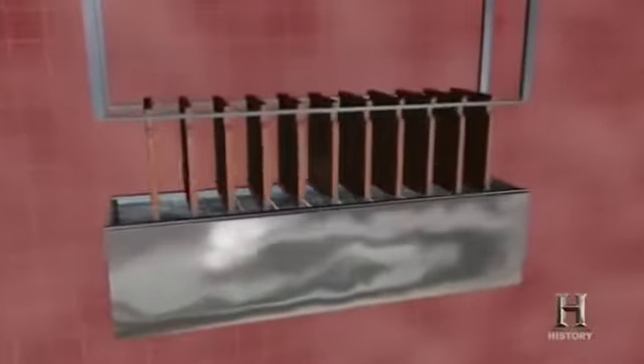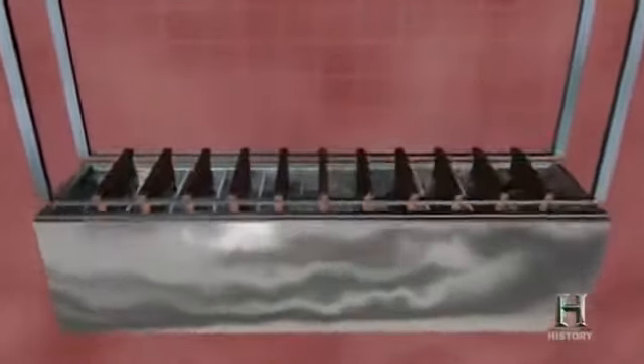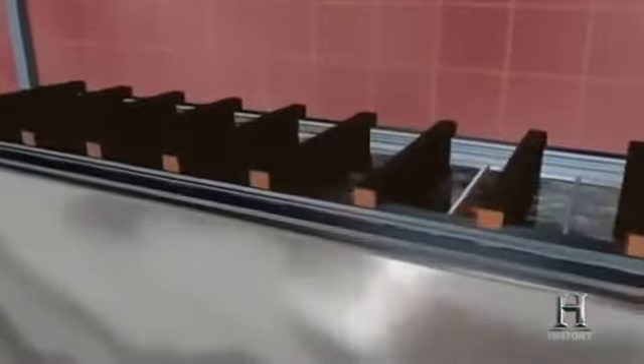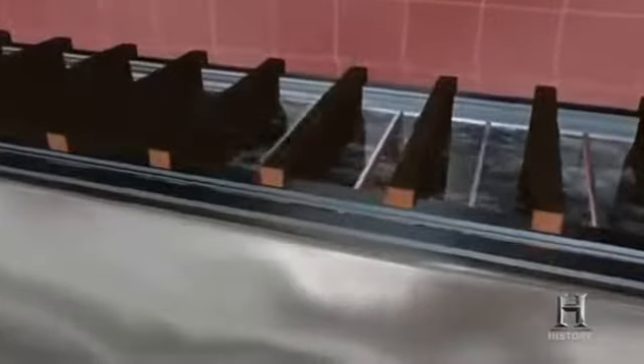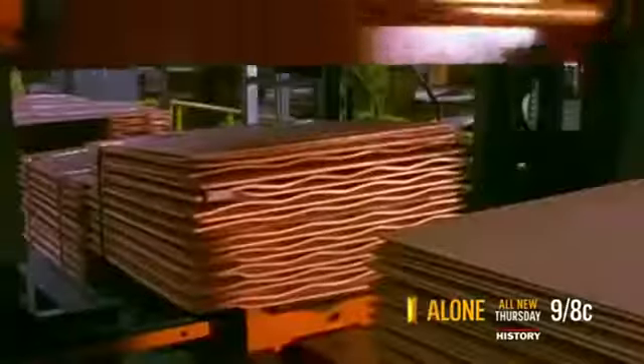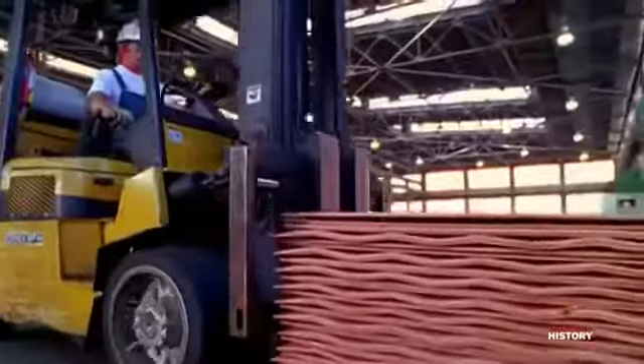But 99.6% is not pure enough. Racks of anodes are lowered into an acid solution interlaced with stainless steel cathodes. For 10 days, an electric current passes between anode and cathode, causing copper ions to dissolve off the anode and redeposit on the cathode as 99.99% pure. 1 ton of ore from the mine has yielded 12 pounds of refined copper.